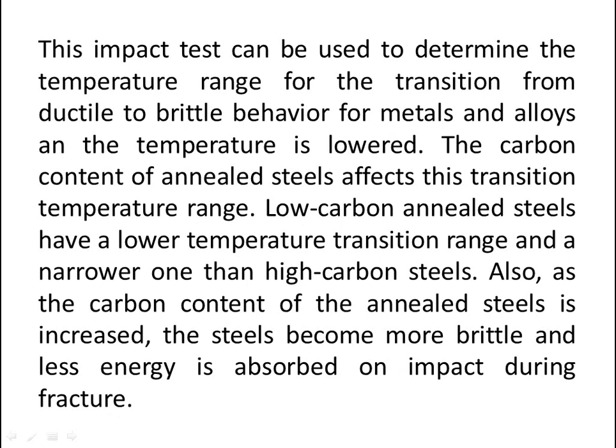This impact test can be used to determine the temperature range for the transition from ductile to brittle behavior for metals and alloys. As the temperature is lowered, the carbon content of annealed steels affects this transition temperature range. Low carbon annealed steels have a lower and narrower transition temperature range than high carbon steels. Also, as the carbon content of the annealed steels is increased, the steels become more brittle and less energy is absorbed on impact during fracture.